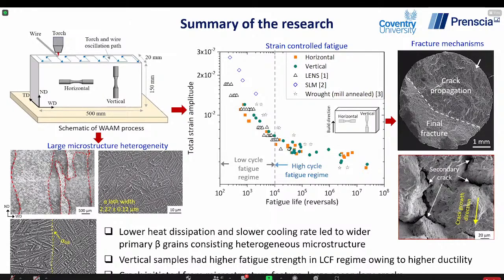However, we have found some alpha grain boundaries where we have some colony microstructure on one side, and on the other side there is a typical basket weave microstructure. So we can expect that with such microstructure heterogeneity, there will be some influence on the cyclic performance.